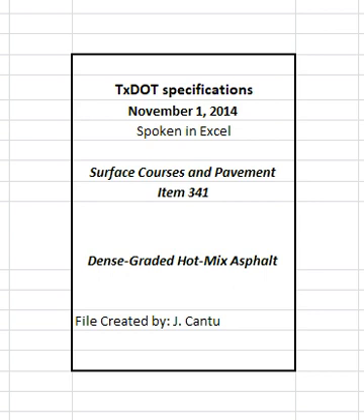Table 10. Hamburg wheel test requirements. See table in specifications. 1. When the rut depth at the required minimum number of passes is less than 3 mm, the engineer may require the contractor to increase the target laboratory molded density, TGC, by 0.5% to no more than 97.5%, or lower the Ndesign level, SGC, to no less than 35 gyrations. 2. May be decreased to no less than 5,000 passes when shown on the plans. 3. May be decreased to no less than 10,000 passes when shown on the plans.